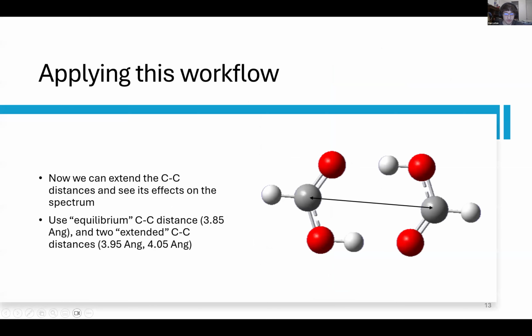So it looks like it works well for the regular formic acid, but we're looking at how this CC distance is going to affect the spectrum. So now we're ready to actually extend this. Before, when I was building the formic acid dimer using computational software, the CC distance for the minimum energy configuration was 3.85 angstroms. That was the value I used for the previous spectrum.